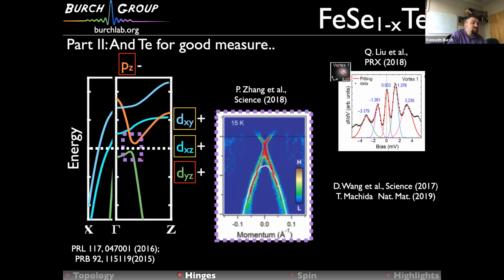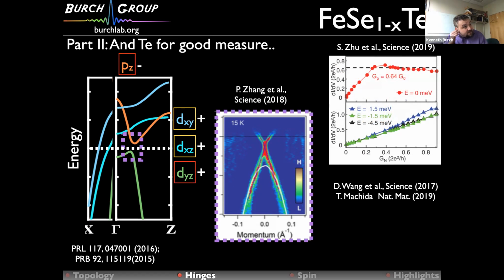But nonetheless, there's also been a variety of different STM works, and I'm sure I'm leaving some out, that have found zero bias peaks inside vortices in this material. And one of the nice things here is that you're sort of in a good limit in terms of being able to observe such things. And this has been seen by now multiple groups in multiple vortices and so on. And there's even a recent observation that suggests that the tunneling into these vortices, into these Majoranas, is quantized as it should be.